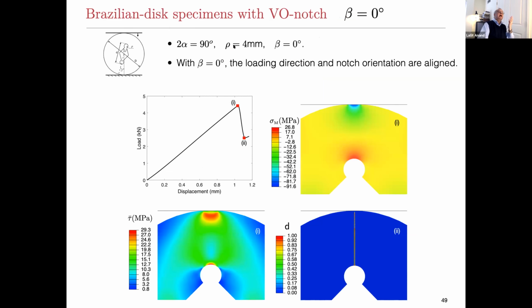We have the parameters calibrated, so you can do the simulation, and what you find is that crazing happens again when the mean normal stress and tau bar reach a critical value, and then the craze will propagate. For beta equal to 0, that means it's vertical, it'll propagate in that direction, as is to be expected, because the maximum principal stress direction is horizontal. And when it hits the boundary, you get this little upturn numerically, but physically, once it hits the platen, it's going to fly off. So don't worry about this upturn.